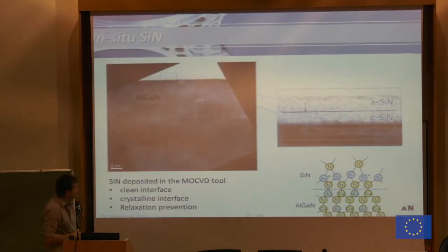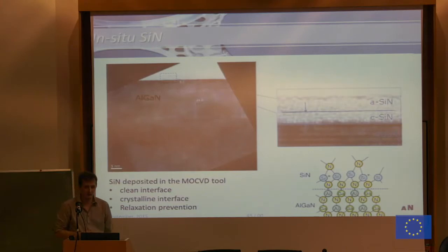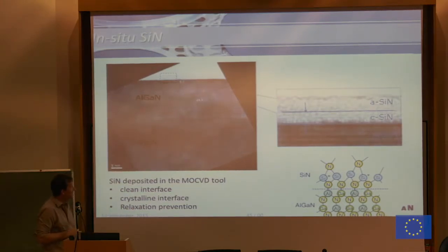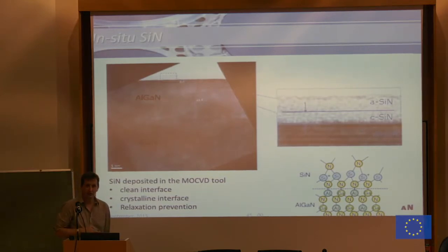Now there's one way to prevent this. It is something we heavily promote at Epigan, so that's why it is in the presentation. In fact, you can grow this passivation layer that I discussed already before, this in situ silicon nitride. You can grow it in your MOCVD reactor.